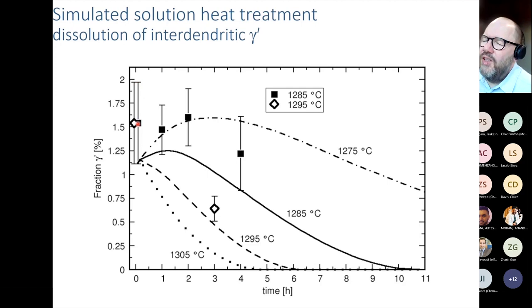So the error bars are actually not very large, but relative to the amount of gamma prime, they appear very, very massive. But we find overall, and that's the important thing, that the trend of the dissolution for the different temperatures, 1285 and 1295, is very, very similar. Finding that at 1285, we have something like an incubation period before the dissolution kicks in, and then we see a very rapid drop in gamma prime fraction. While for 1295, we have a very early onset of dissolution, so we end up after 3 hours with a much, much smaller fraction of gamma prime.